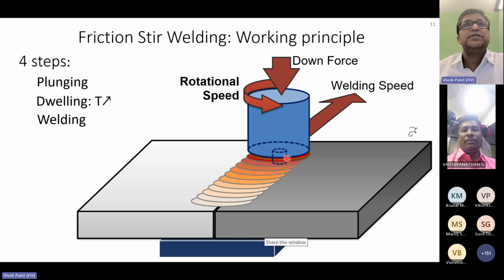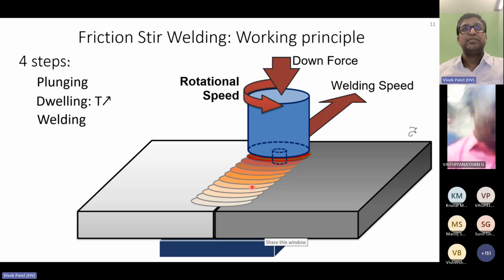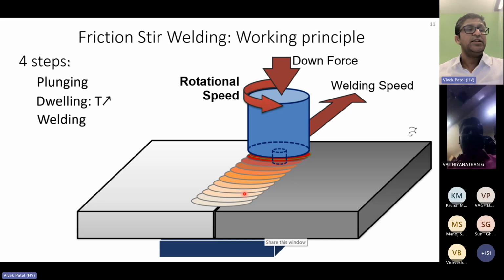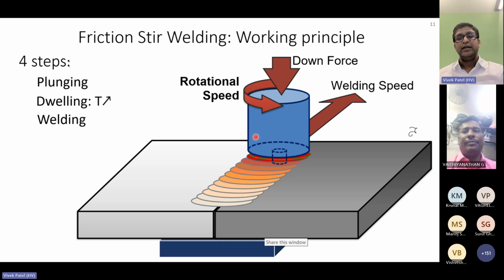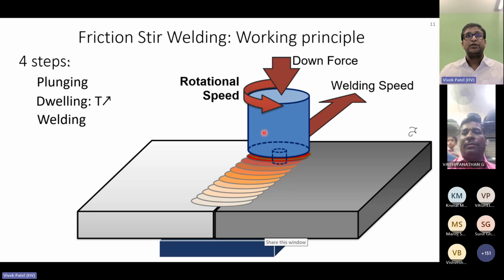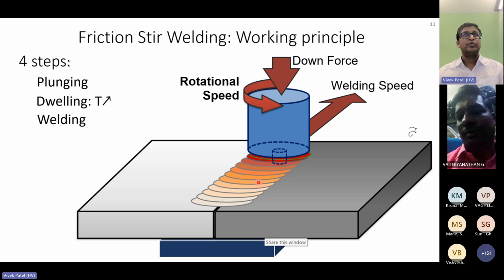And if you look at the process parameters, how the process is controlled or governed: once you have the right dimension of the tool, then the process temperature, or I would say the heat input, is controlled by these three red arrows. The first one is the rotational speed. So the higher the rotation speed, the more friction, so you generate more heat.